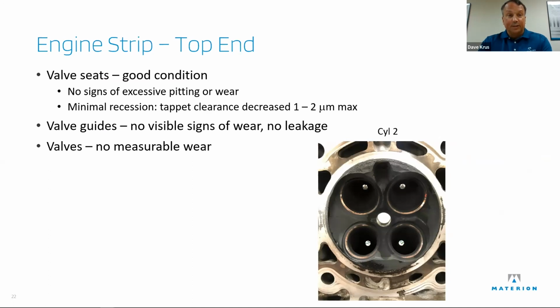No signs of additional leakage or wear. There was a little crust buildup in one case where they got a little leakage, but once that came off, it was fine. And nowhere on the valve. So the valves didn't do any worse for having these high durability. Actually, it probably did a little bit better, as I said, because they should be gentler than an iron-based material.